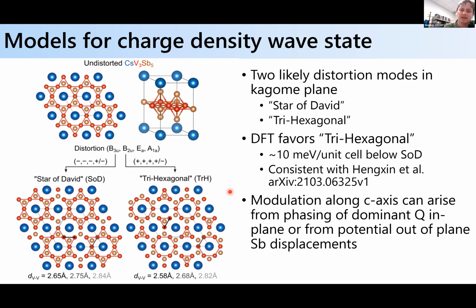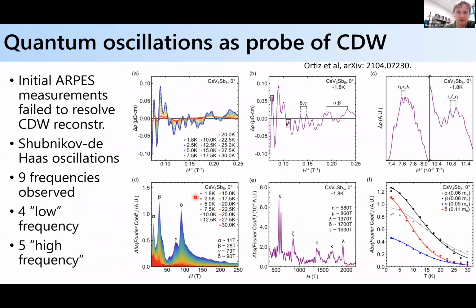So again, trying to resolve whether it's realizing a Star of David or a trihexagonal structure was some of the work that we've been doing in the past several months. One of the ways of doing this is that the initial photoemission data, when we looked at the electronic structure, failed to resolve a reconstruction of the Fermi surface due to the CDW. And that was probably because the resolution of the measurements wasn't sufficient.